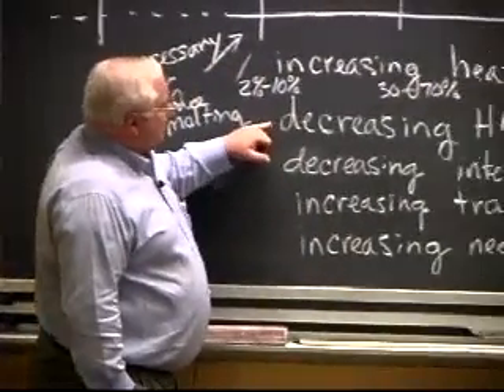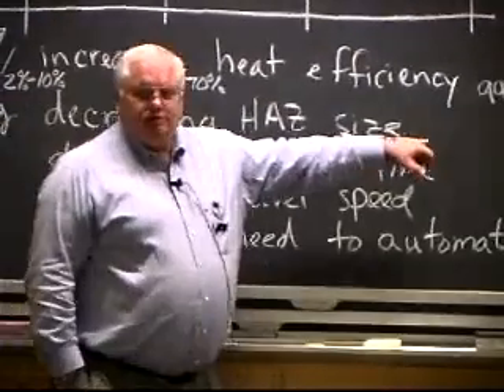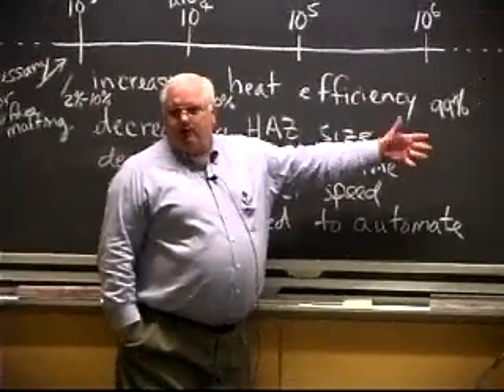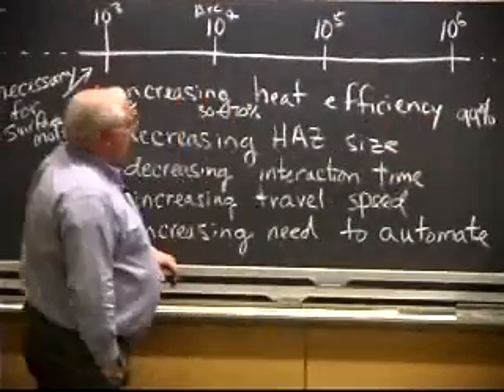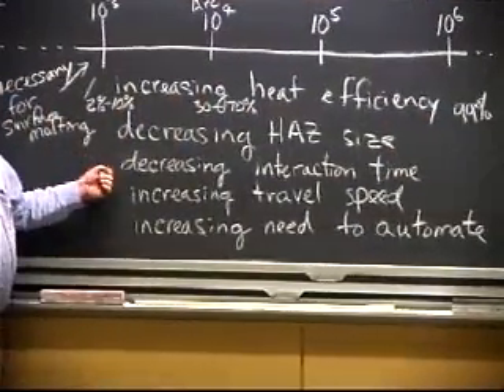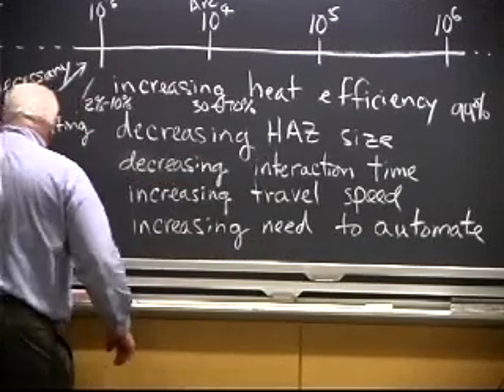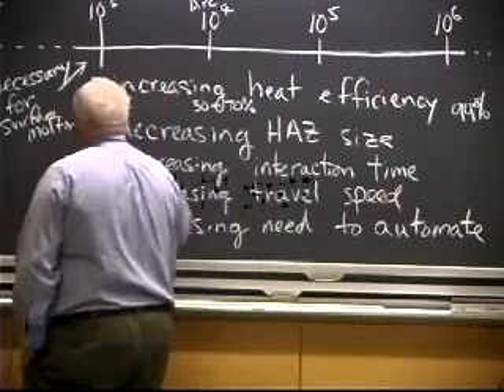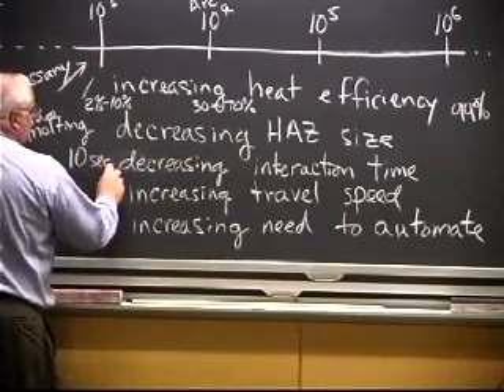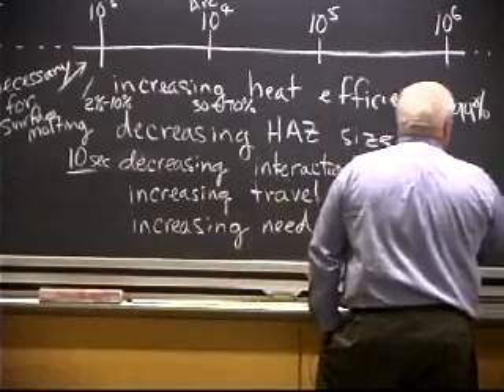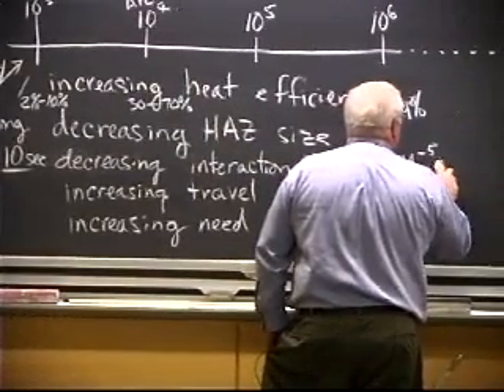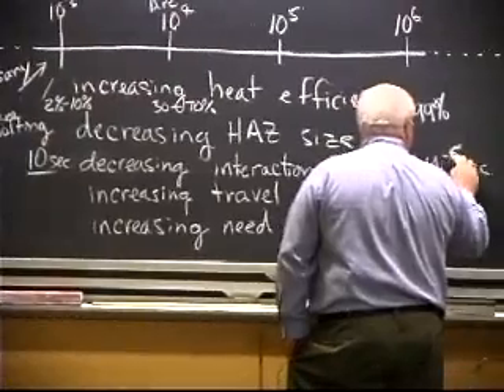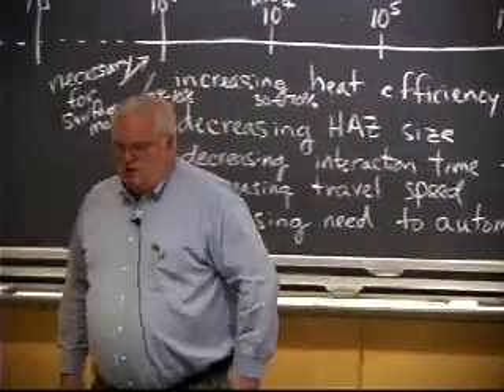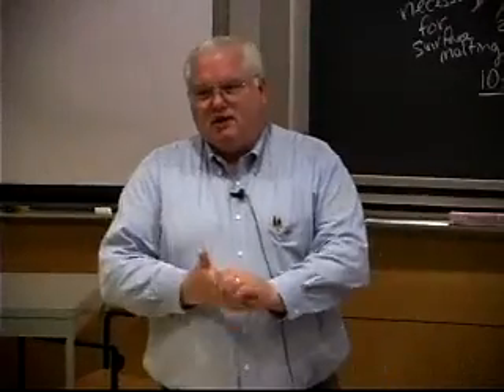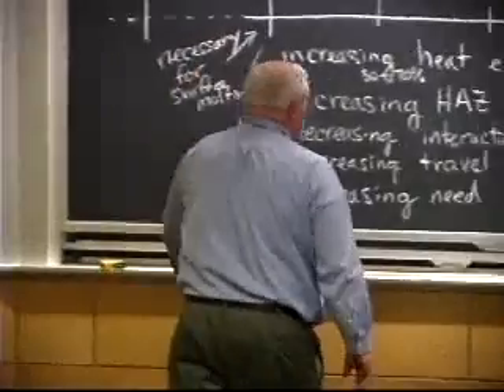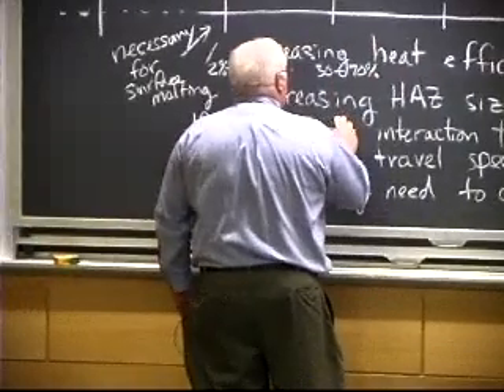So, decreasing heat affected zone size, going from several centimeters down to millimeters, but it could be 1, it could be 10 millimeters, depending on the width of the fusion zone. Decreasing interaction time, obviously it's slower over here and shorter over there. The typical melting time could be 10 seconds on this side, and 10 to the minus 5, or let's just call it 10 to the minus 6 seconds over here. I have seen melting with electron beams and laser welds that are that short. And in the middle, arc welding has an interaction time on the order of 1/10 of a second.